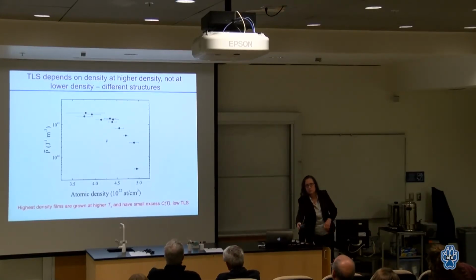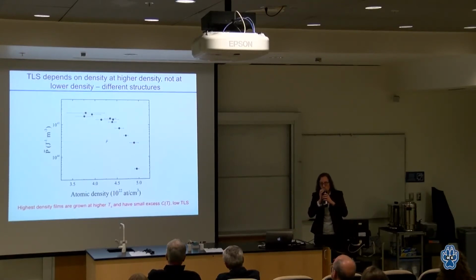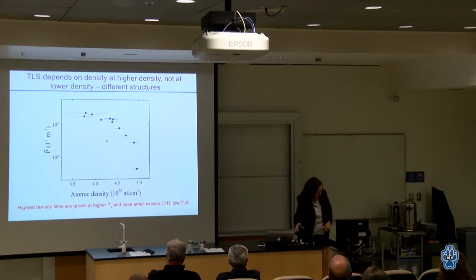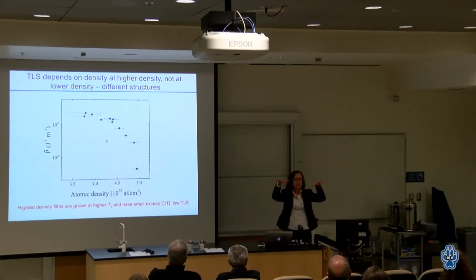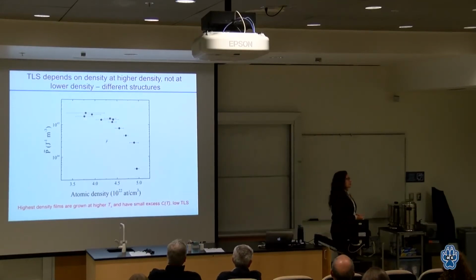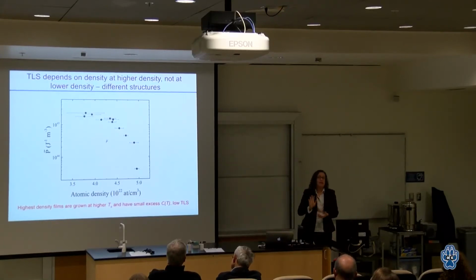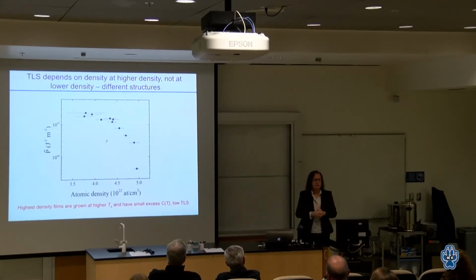Right, but I imagine if the film gets really thick, you should start to see isotropic behavior. I don't think so. We've grown pretty thick, and it will continue growing that way because there's always a surface. To the limit that we've grown pretty thick films, they're still perpendicular. I'm talking about a millimeter range, something really close to a bulk material. As long as it was grown, it remembers that it was grown. It had those surfaces that form. So even at a millimeter, it would still be there.